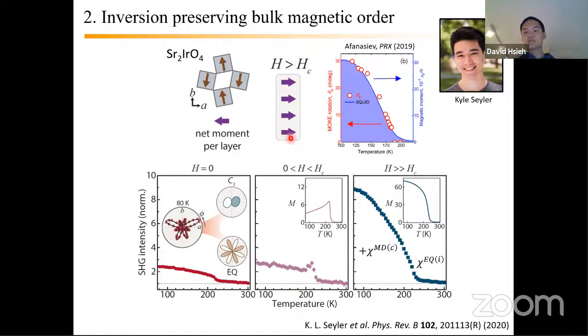And that's borne out, for example, in static magneto-optical Kerr rotation experiments. You can see below TNeel, you have a Kerr signal that turns on. And in SHG, that leads to another process that we've identified as originating from the C-type magnetic dipole SHG channel. And you can see that in these curves, for example, at H equals zero, that's the curve I showed you earlier. You only have this surface magnetic dipole term. But once you start turning on a field, you get another term that's proportional to the magnetization.